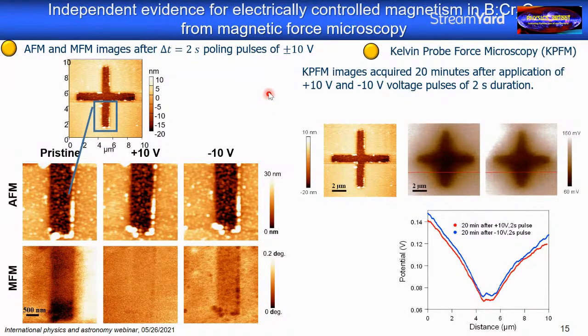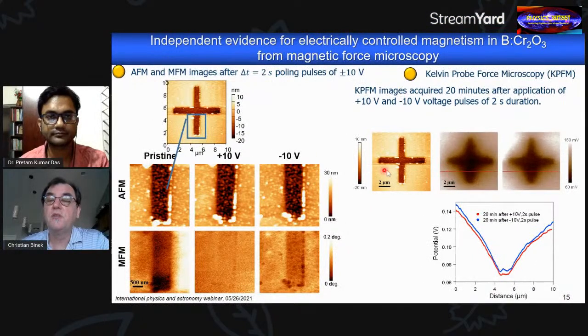And my colleagues were cautious and said there is always a possibility for artifacts. So they did this Kelvin probe microscopy in addition as a cross-check to figure out if we could suffer from any charging effects that could mimic such a behavior. And the answer is no. Whether you apply a positive or negative voltage, you basically see the same Kelvin probe signal when you scan across this leg here of the Hall bar.